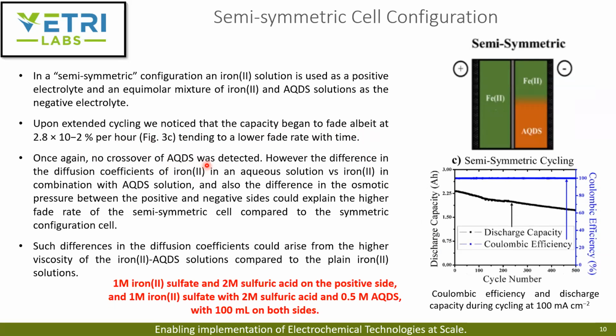However, the difference in the diffusion coefficient of iron 2 plus in an aqueous solution versus iron 2 plus in the combination of an organic solution like AQDS, and also the difference in the osmotic pressure between the positive and the negative sides, can explain why there is a higher fading rate, because in the symmetric cycling, they didn't see the fading rate, right? And here, in the semi-symmetric cycle, they do have a fading rate at a higher rate, and they attribute this to all these three different factors. So the difference in the diffusion coefficient can also arise from the higher viscosity of the iron 2 AQDS solution, because you have an organic solution compared to a pure iron 2 plus aqueous solution.